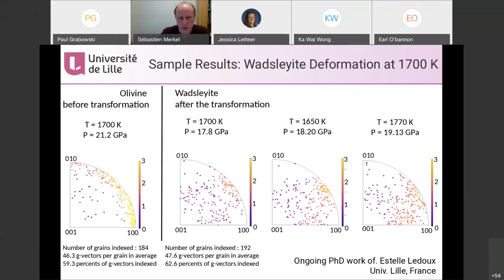Pressure goes down due to the phase transformation, and then we keep increasing pressure to 18 GPa, 19 GPa, and all along the way we keep the sample at 1700 Kelvin, and at each step in pressure we stop the pressure increase, collect multi-grain diffraction, and then go on and go again. And so the difference between the previous type of experiment and this one is the temperature. We actually can work at several thousands of degrees and stay there for hours. We've actually been able to do such experiments over like 20 hours or so.